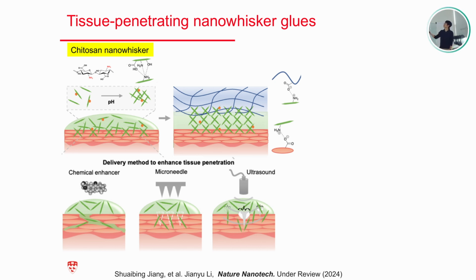And the nice feature about this kind of particle is it has a very high aspect ratio, as you see in this kind of schematic. So we show that in the case of the chitosan nanowhiskers, the same kind of composition we used for the previous work, but in this case in a nanoparticle or nanocrystal form. This one has a very long size and very small cross section, much more like a nano needle.